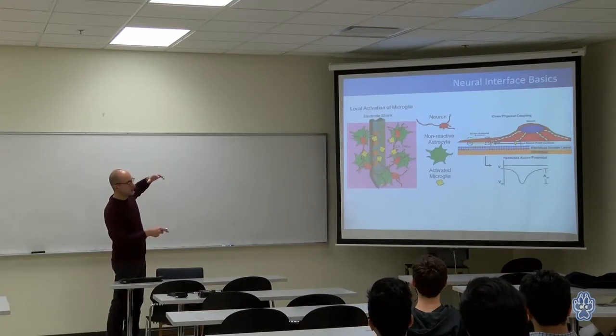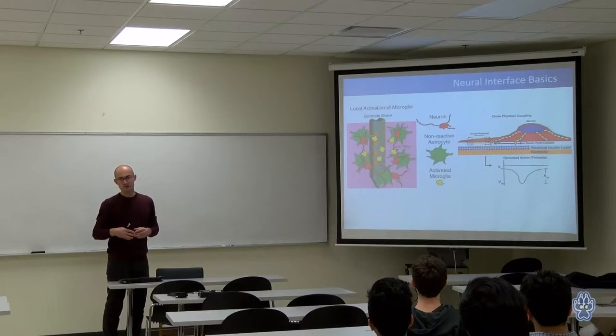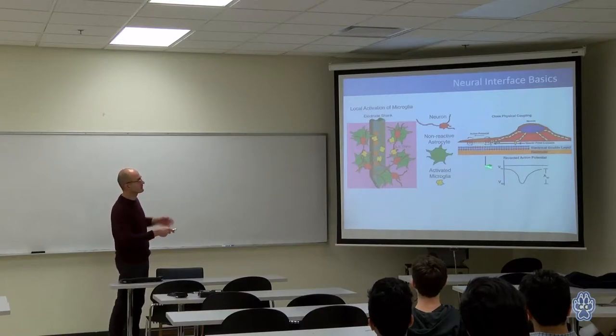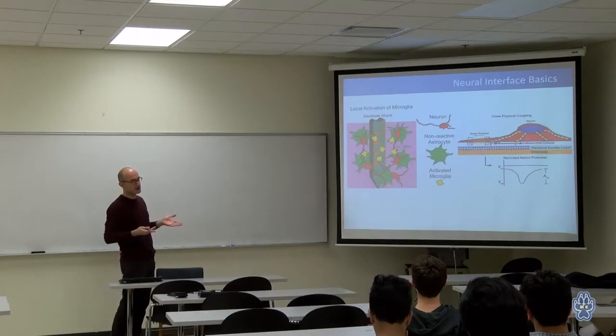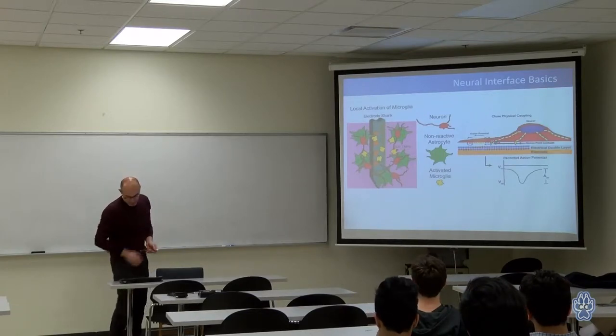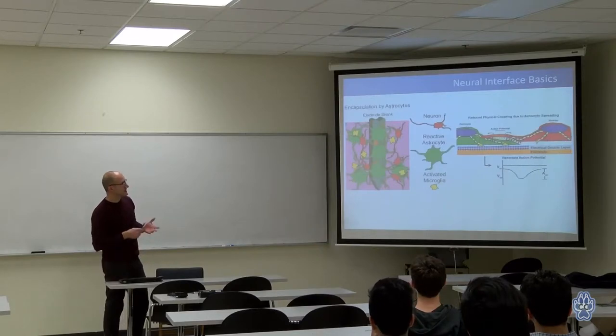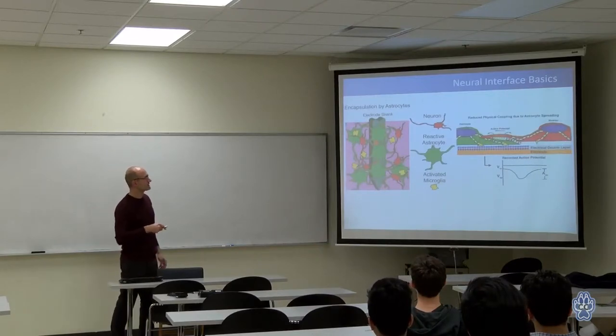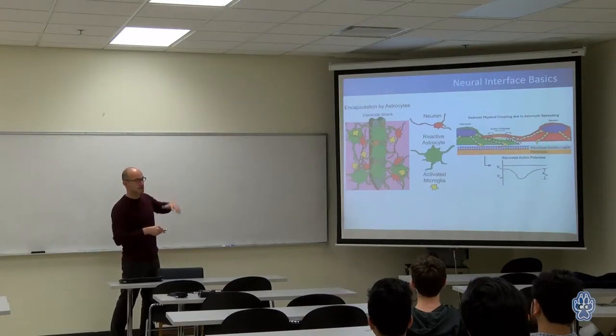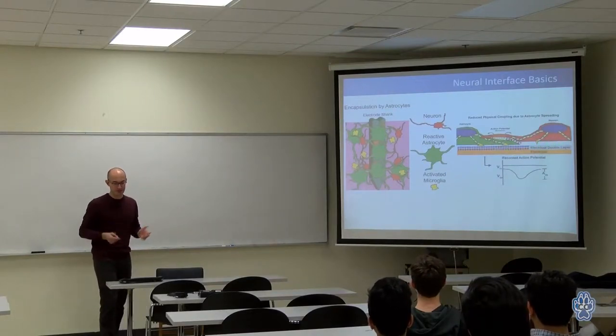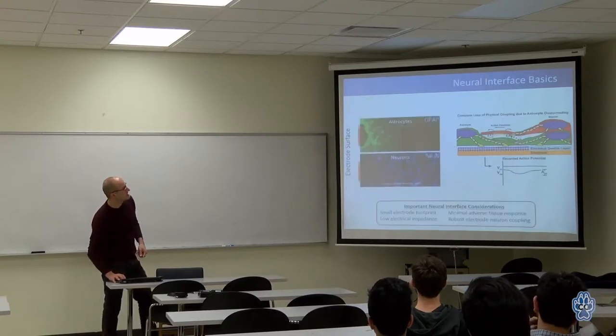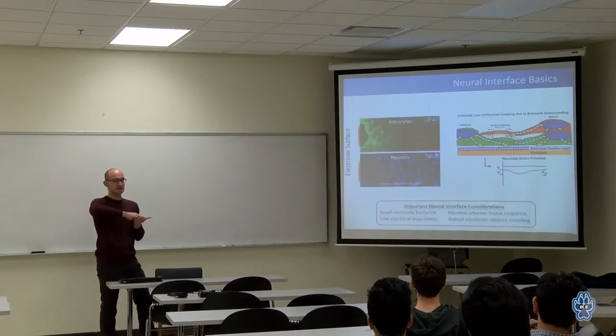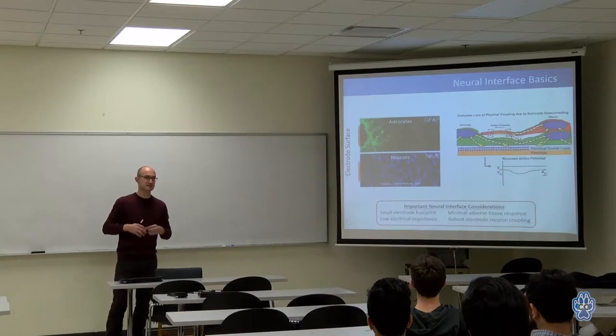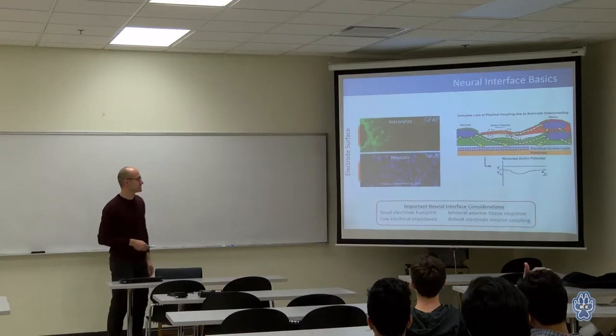It's kind of an emitter-receiver problem, or transmitter-receiver problem. If you have the two closer together, then you have a higher signal-to-noise ratio. But due to this scarring, if the astrocytes reacting to the surface begin to go in between the neurons and the electrode, then you begin to lose signal-to-noise ratio. So in essence, we want the neurons to attach to the surface, but the astrocytes, the scar-forming cells, to be pushed away from the surface.